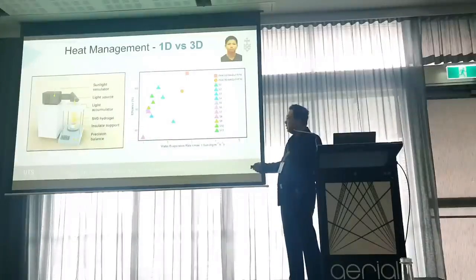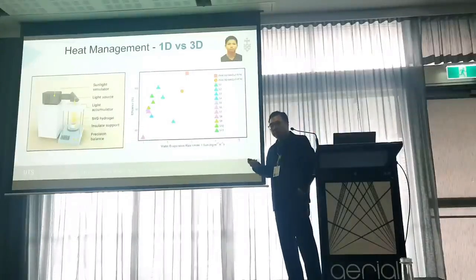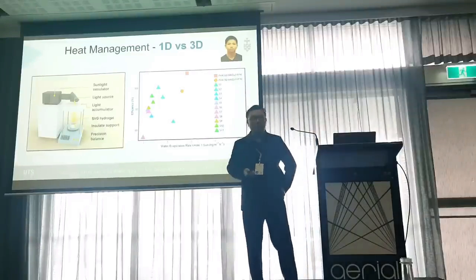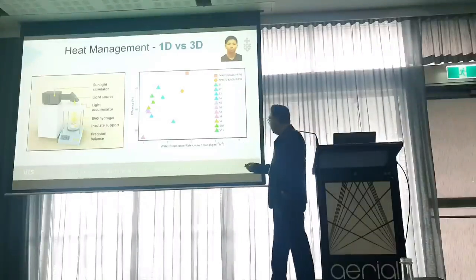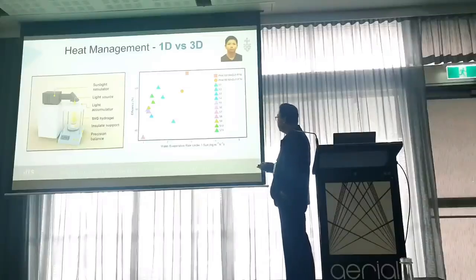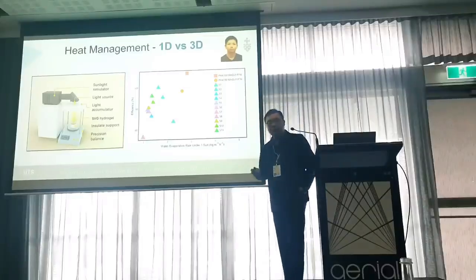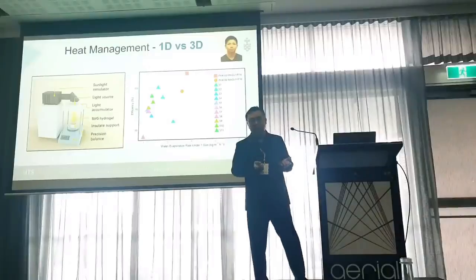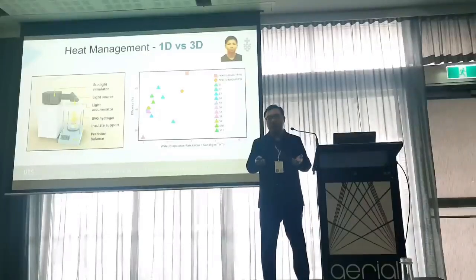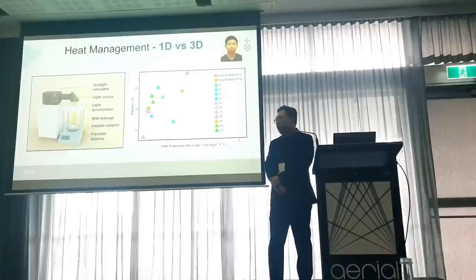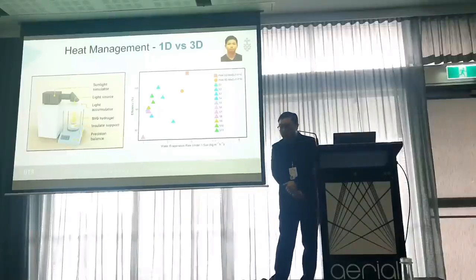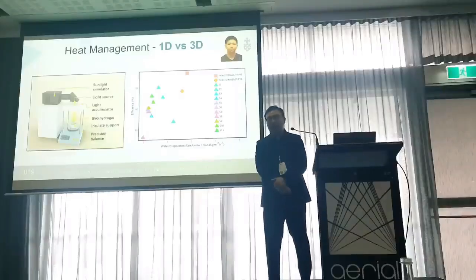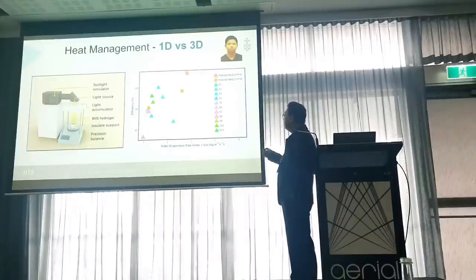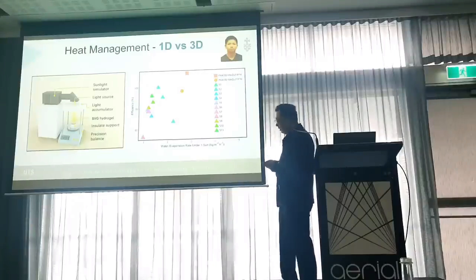And then we use this homemade setup to test the solar vapor generation efficiency, or the water evaporation rate, of our hydrogel materials. And the results are summarized in this table. As you can see, the PVA hydrogels with 1D nanorods show the highest SVG performance compared to all the semiconductor-based hydrogel systems. They achieve about 2.8 kilograms per square meter per hour, as well as very high solar-to-vapor efficiency. And this performance is definitely better than the 3D nanoparticle one.